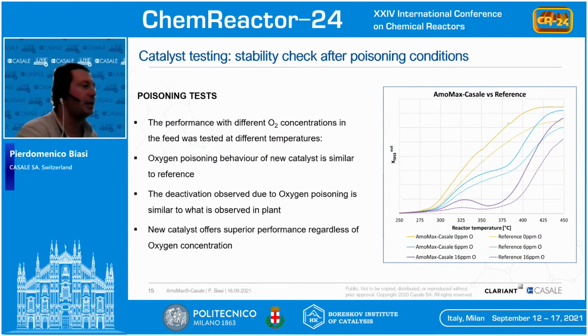And as you can see, during the catalyst activation, when the catalyst is active, especially with the 6 ppm, you have a problem here, because you cannot make the proper light-off of the catalyst. So we saw already here that the new Ammonia Casale catalyst was more performing, especially here where 10 degrees of temperature make a big difference in the economics of the plant.